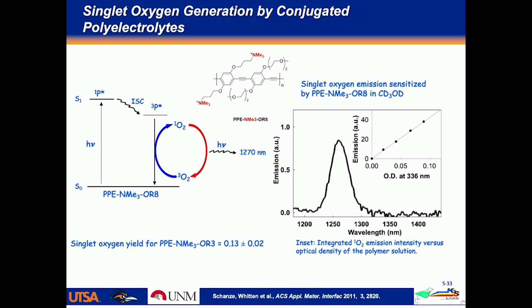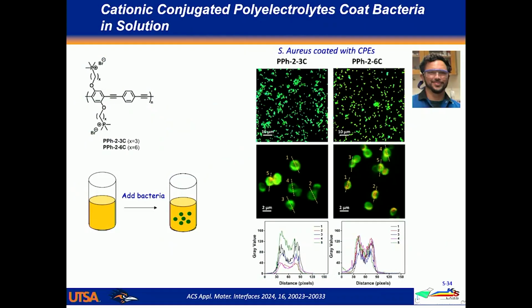This polyelectrolyte, under the conditions that I talk about here, generates singlet oxygen at a quantum yield of about 13%. So it's a moderately efficient singlet oxygen generator. So that's the first part of the story. The second part is what happens if you mix these polyelectrolytes with a suspension of bacteria. It turns out they very effectively and very rapidly coat the bacteria.